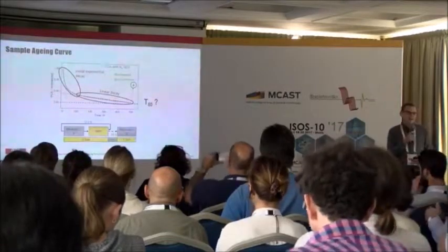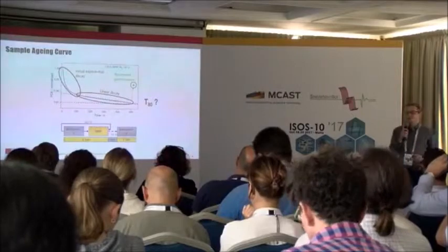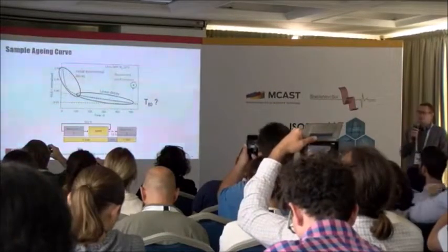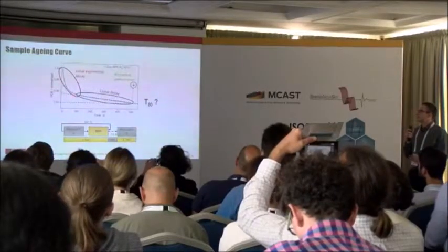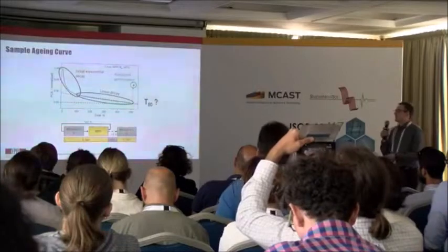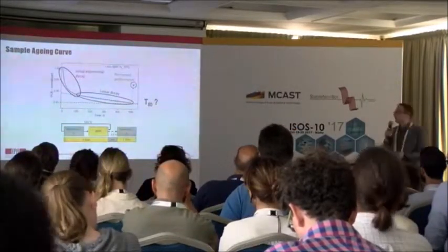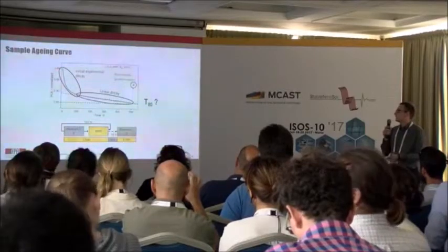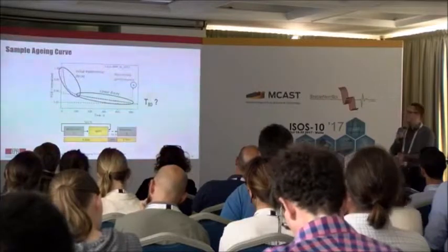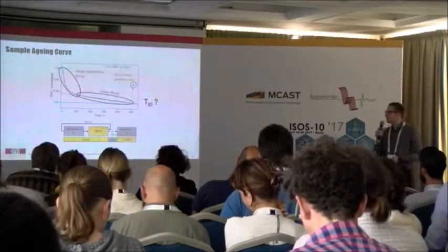So when we measure the devices, and we would call them well-behaved, we often see this two-regime behavior with the initial fast exponential decay and a slower linear decay. And then if we leave the device in the dark, we see the recovery of this initial part. It's almost complete in most of the cases. Slightly lower on average than this, but still corresponds pretty well.